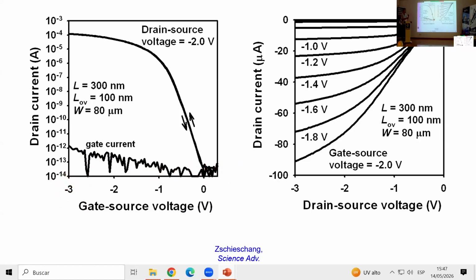And that's a testament to the fact that the off-state leakage current, both through the gate dielectric and through the semiconductor, is in fact as small as we can hope for it to be. The on-state drain current here is 100 microamps. And so the on-off current ratio is 10 orders of magnitude. So this is the highest on-off current ratio that's been reported for organic TFTs. And it's actually higher than for many zinc oxide transistors that we're able to find in the literature. So this confirms the equations that I was using just a few minutes ago.